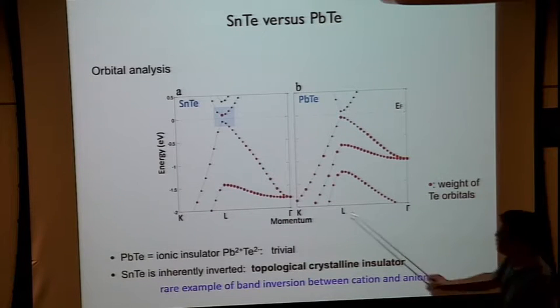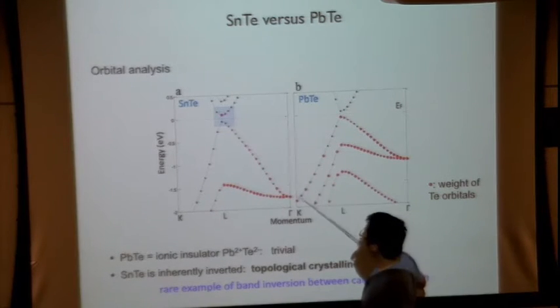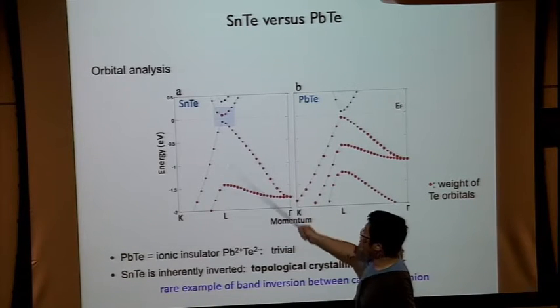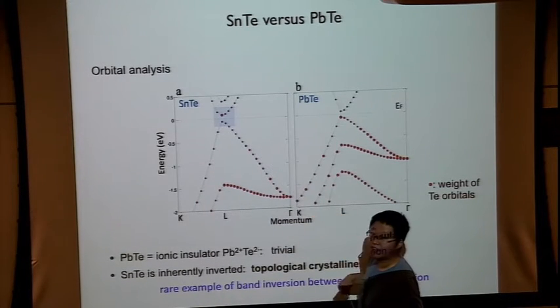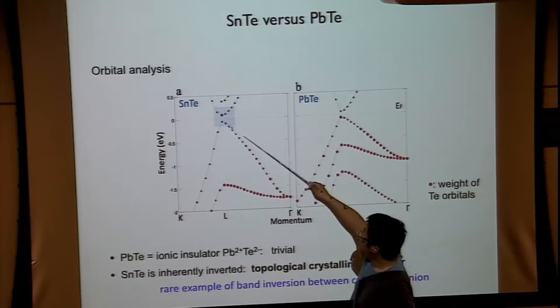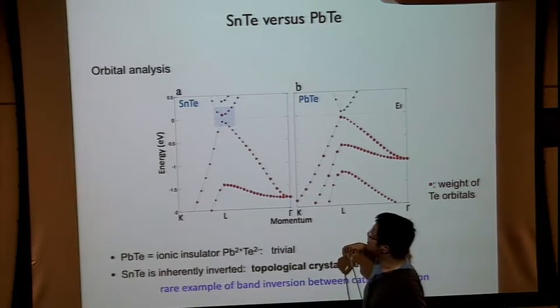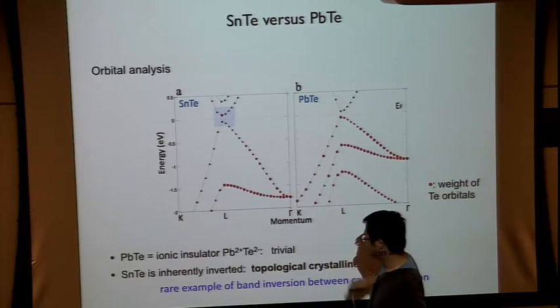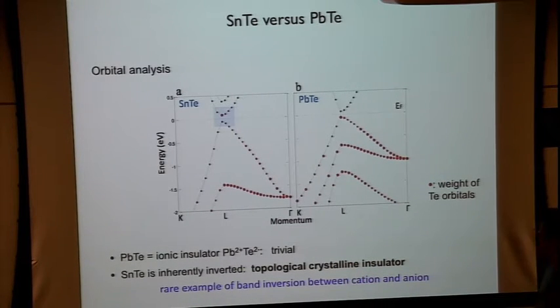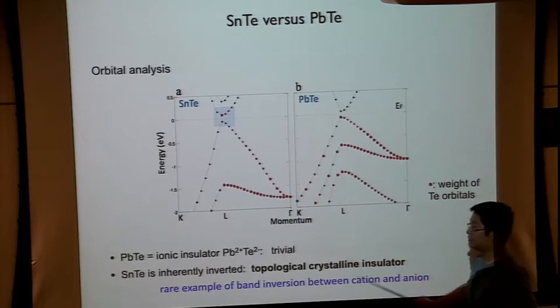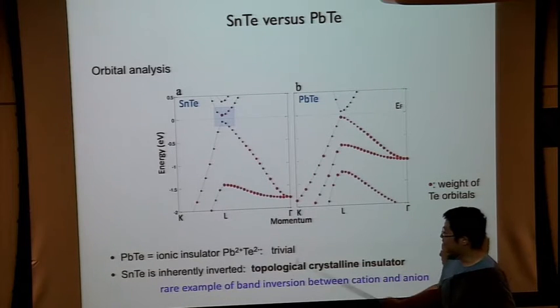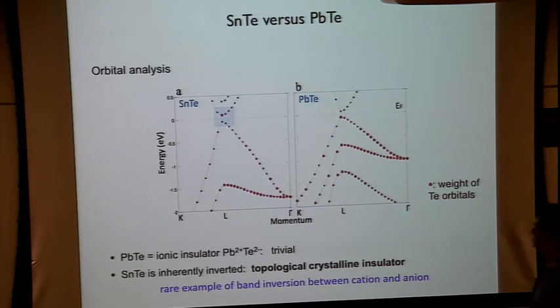On the other hand, if you look at tin telluride, the occupied states are mostly tellurium in momentum space, but just near the top of the valence band, the wave function in the occupied states comes from tin, from the cation. So this tells us that tin telluride is intrinsically inverted. The wave function has a mixture of ionicity and covalency. Combined with the fact that there has to be a topological difference between the two, that led us to the conclusion that tin telluride must be topologically non-trivial, protected by mirror symmetry.